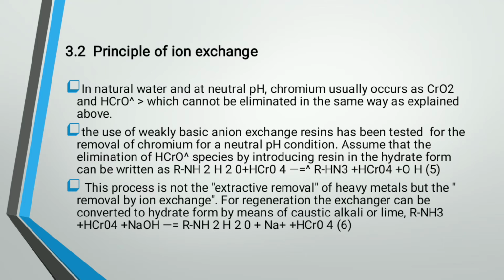The use of weakly basic anion exchange resins has been tested for the removal of chromium at neutral pH condition. Assume that the elimination of HCrO4- species by introducing resin in the hydrate form can be written as the following equation. This process is not extractive removal of heavy metals but removal by ion exchange. For regeneration, the exchanger can be converted to hydrate form by means of caustic, alkali or lime.